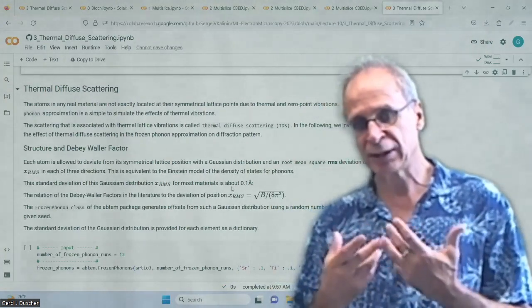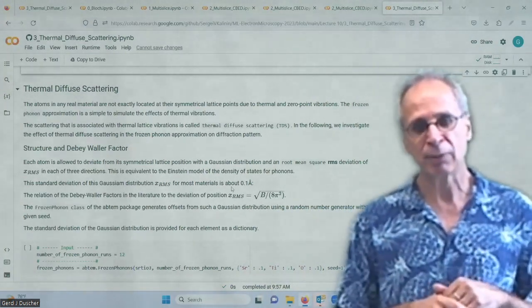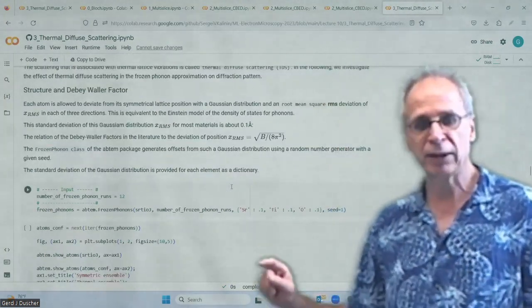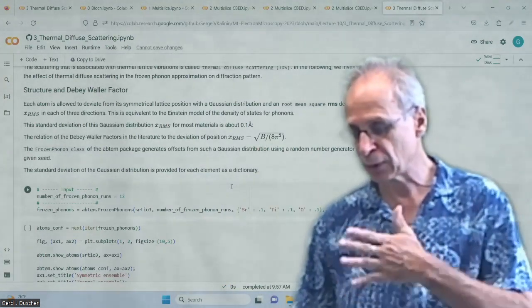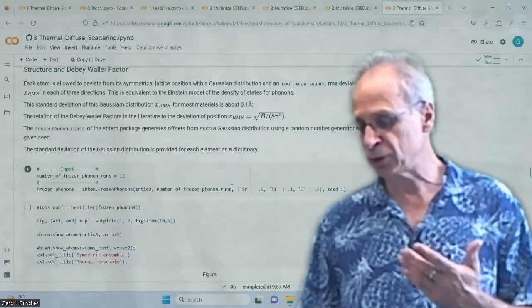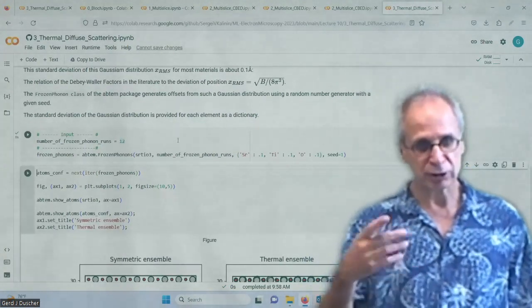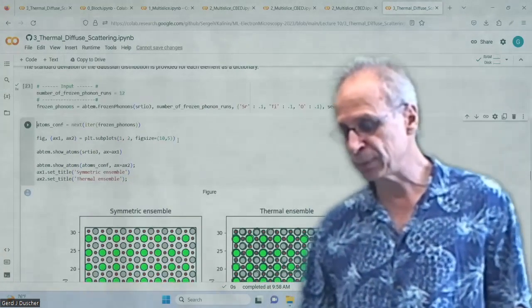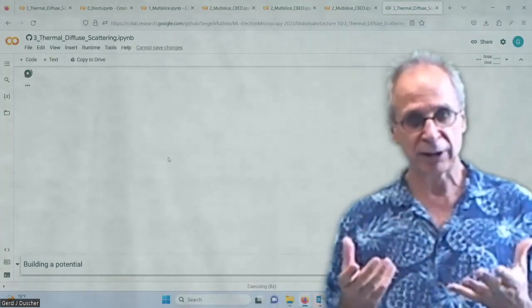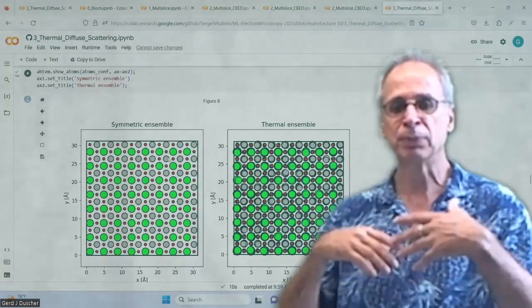The way we treat thermal diffuse scattering is with the so-called frozen phonon approximation. We rattle the atoms a little bit, depending on the Debye-Waller factor, which gives us how much they deviate from their perfect positions. We do that randomly. In this case I will add 12 of them — so instead of one calculation, we have 12 independent ones. Obviously that could be very nicely farmed out to 12 different processors. The Fourier transformation and all of that is nicely parallelizable. We go from a single calculation to a thermal ensemble.